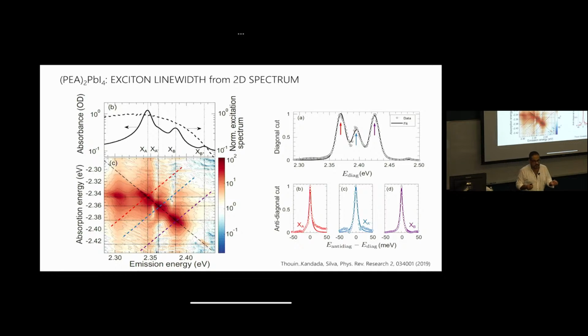It's not like in the sample there's a region that has exciton A and another region that has exciton B because it's a messy sample. These are fundamentally part of the electronic structure. They're cross peaks that are correlations between these. They share common ground states. So these are fundamentally part of the optical structure of the sample. So that's nice to show.